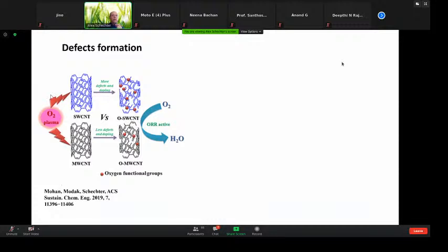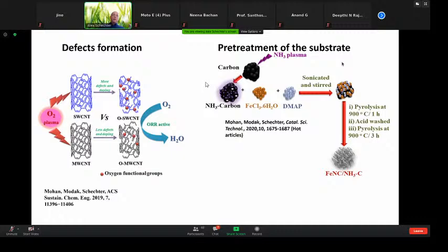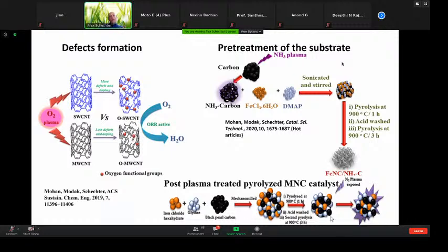Then we have developed a way, using a cold plasma, to introduce defects into CNTs and other graphitic structures, showing enhancement of oxygen reduction even without using any metal to do the reaction. And this is very important. This is a completely metal-free catalyst. And then we took the plasma and we activated the catalyst support, and showed that it's becoming even more active towards oxygen reduction using a different precursor, CNT, or taking it after the formation of the catalyst and exposing it to nitrogen plasma, showing again a very pronounced enhancement of the activity. Again, no platinum at all.